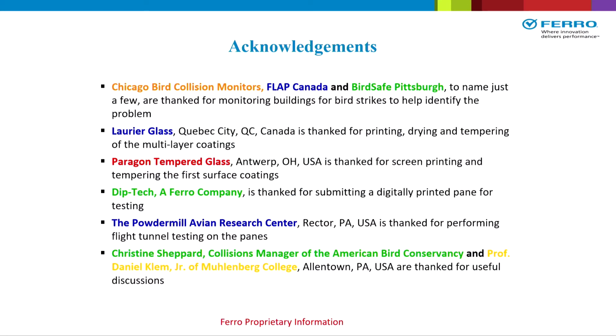Laurier Glass in Quebec City, Canada, is thanked for the printing, drying, and tempering of the multi-layer coatings, because they had to print, dry, and fire 5 times on top of each other on the same piece of glass to build up the 5-layer coating. So it was nice work. Thank them a lot. Paragon Tempered Glass in Antwerp, Ohio, is thanked for the screen printing and tempering of the first surface coatings. And our new colleagues in Diptech are thanked for submitting the digitally printed pane for testing.